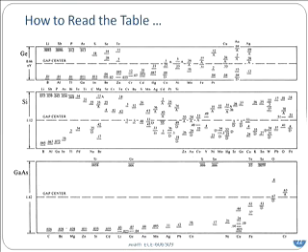Now, you can see correspondingly all the acceptor levels. The boron we just discussed, 0.01 eV, just above the valence band, and so on and so forth. You can also see that there are things marked as an A. So, for example, copper in germanium on the top side, on the right-hand side, you can see it is a 0.26, but underneath an A. That means that level talks to the valence band, and it is actually an acceptor, not a donor. So this information we will need over and over again when we do actual calculations.